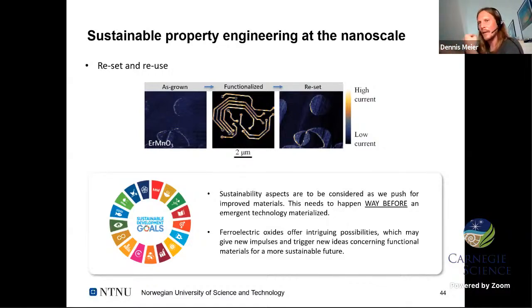How much that spreads out and how much every single dislocation contributes, we cannot say from the experiments. So we are integrating over a dislocation-rich area. Yeah, so it could be that they are just disrupting the path to ground. It could be that we only see that area because with CAFM, when we measure, we are only probing something like 50 to 100 nanometers into the depth. This is something we need to study with higher resolution. Right now, we're averaging. I can just say that the dislocations reduce the conductance, not what an individual one does. I would love to know that, but we have no access right now experimentally.